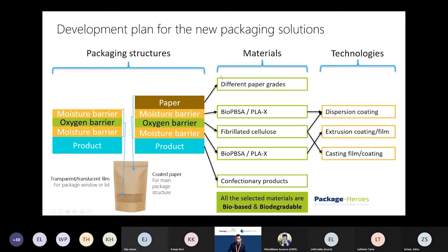And we used different paper grades in lab, but on the pilot, we had decided to go with one particular paper grade. For moisture barrier, we had two options. One was bio-PBSA and the other one was modified PLA. For oxygen barrier, we had fibrillated cellulose. You can call it microfibrillated cellulose or cellulose microfibers. And then we had the other moisture barrier layer, which was again either bio-PBSA or PLA-X. And the target food product group, as I mentioned already, was confectionery products.